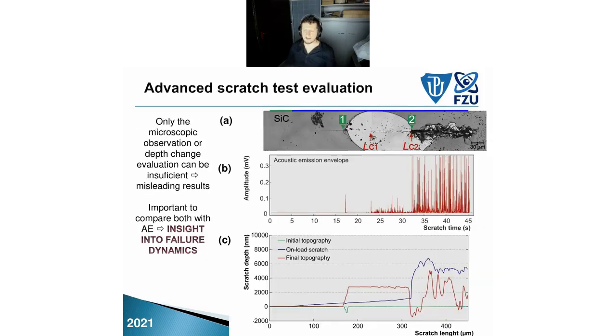Okay, so let's show our evaluation in some specific cases. This is silicon carbide coatings before annealing, and if we use just one or two analyzing procedures, we can be mistaken. If we just look at the residual image, we can see, okay, something cracked here at point 1. So the coating cracked, and here coating and substrate cracked. So it's like a loss of cohesion of both parts.